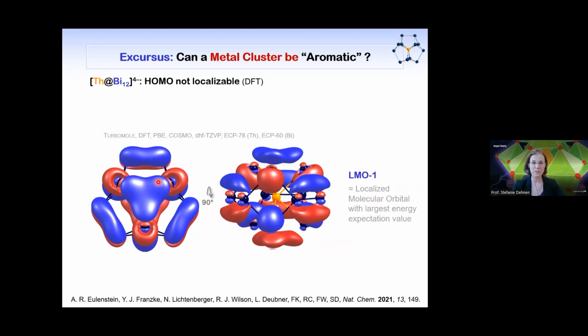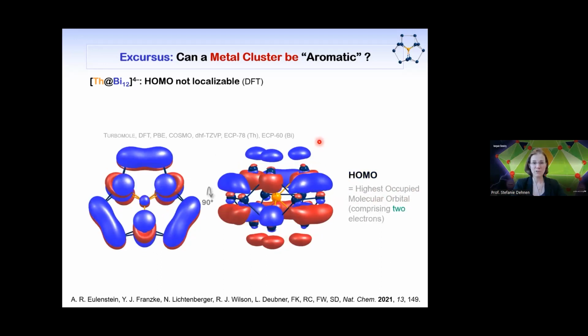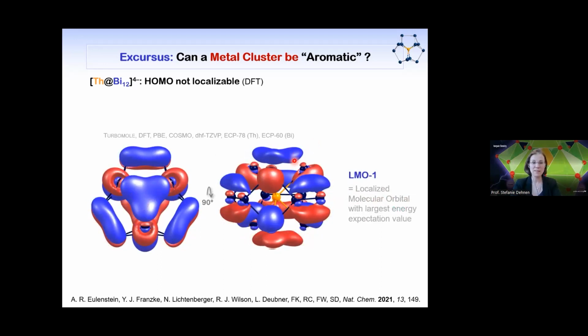This is a mathematic procedure. This is well known. And if you are looking closely to what I just did, I just moved from the HOMO to the so-called LMO, and this is the LMO with the largest energy expectation value, so the highest LMO, if you will. You see not a big difference. It's a little bit different, but not too much. So that tells us that all atoms are actually involved after localization, so it cannot be localized. This is, in contrast, something that happens with all other molecular orbitals. They can be localized, they will be situated between 2 atoms in the end. And this is the big difference. So we have one molecular orbital that could be starting our basis for a ring current.